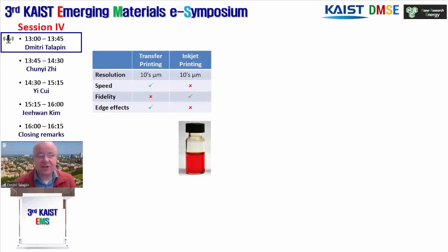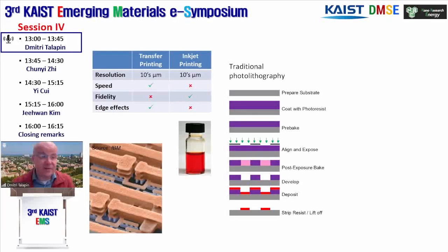And the idea is that patterning of colloidal nanoparticles has traditionally been accomplished by transfer printing or inkjet printing, and those are good techniques. But if you want to push resolution, or especially if you want to push throughput, you can greatly benefit by borrowing ideas from traditional photolithography, where you can define literally billions of circuit elements in a single lithography step. That's what is behind our traditional semiconductor technology. And traditional photolithography uses organic photoresists as a sacrificial pattern defining medium, and upon exposure it changes solubility, and then you can open windows in the photoresist, and then you can do pattern transfer.